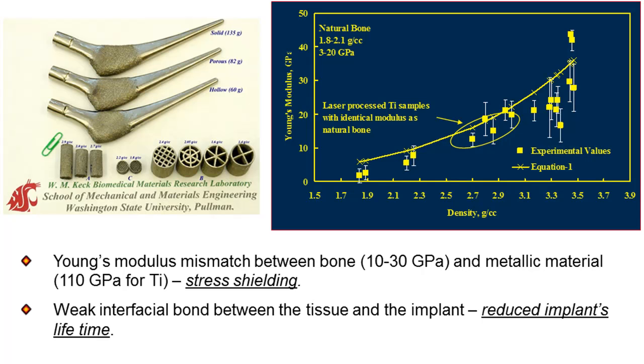But the challenge is because they're solid metal, when they go in as an implant, the stiffness of these materials can have a bad effect on the surrounding bone, because that stiffness difference makes the biomechanical load transfer more into the implant, and that can actually make the surrounding bone weaker. So one hypothesis is: is there anything we could do to lower the stiffness of the implant material?